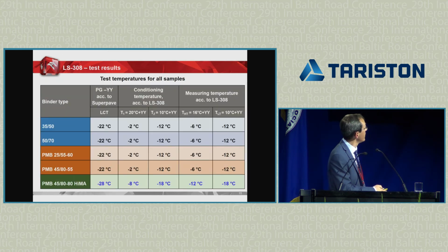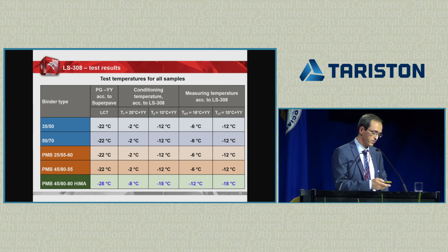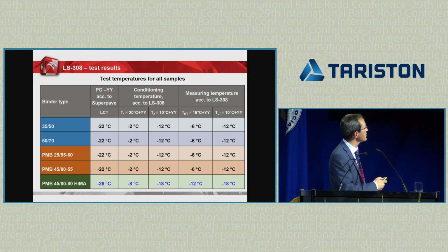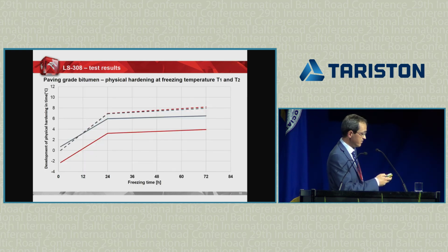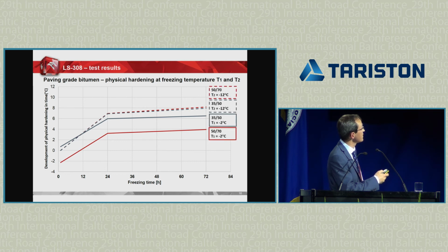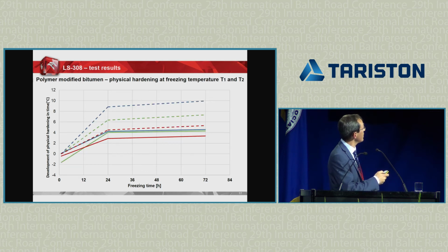Some results. The first, the table with temperatures of conditioning, of freezing the samples. The base is, according to this method, the low critical temperature from the Superpave method, and according to this we calculate the freezing temperatures. And some results, unmodified bitumens with special, let's say, raw materials. We can see that during the first 24 hours, the stiffening is at the highest level. Then between 24 and 72 hours, the stiffening is not so sharp. This is similar for polymer modified bitumen.